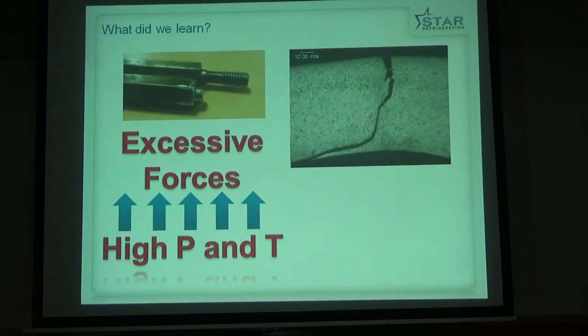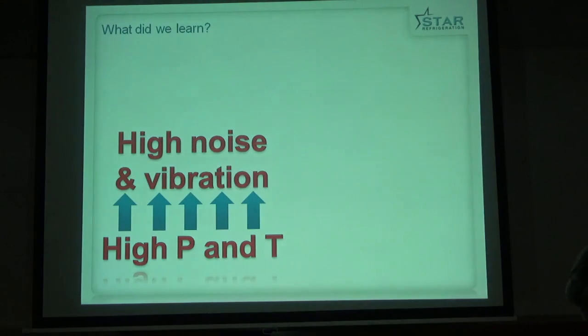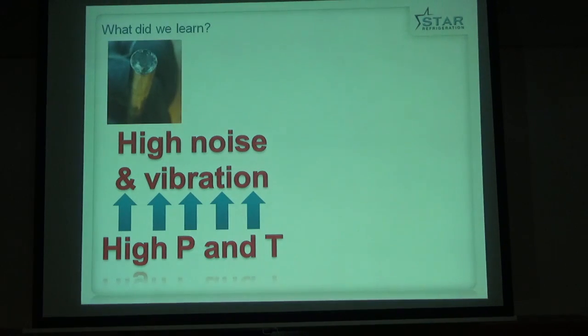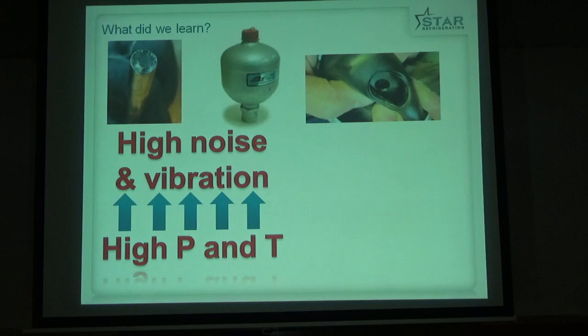And there's a cross-section of the tube. You can see that the crack has propagated all the way through from the initial flaw at the surface. Also high noise and vibration. The vibration also caused some components to break. We fitted HYDAC dampers to the hydraulic circuit to reduce the vibration. This was a great result, very positive. But the rubber of the bellows of the damper wasn't compatible with the ammonia, so we had to think again.